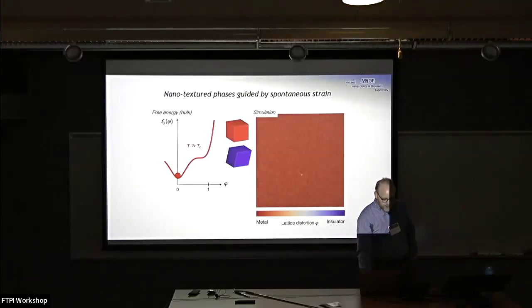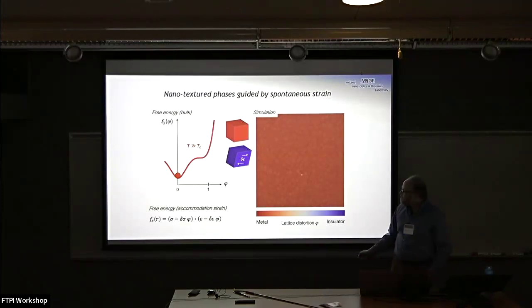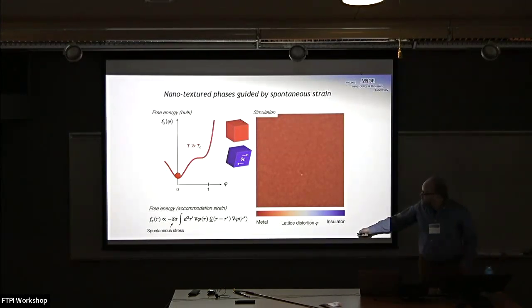And so what if I have a distortion of the lattice? I better go ahead and add my elastic energy into my free energy expression here. Stress times strain. Okay, fine. And without going into many details, we can do some mathematical tricks and realize that it's effectively a long-range interaction between the order parameter at spot R and that at R prime. And what is the nature of this long-range interaction? This is a long-range Green function for strain.